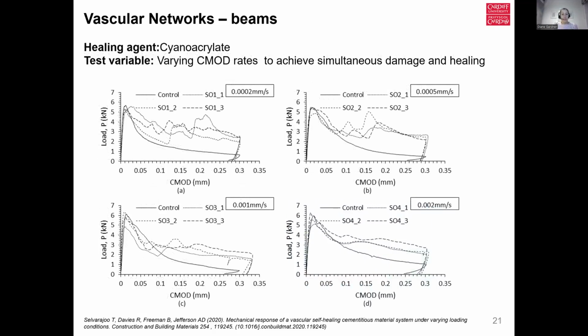Here we have slightly different tests to the ones I've just seen on the previous slide, in that we have varying CMOD rates to achieve simultaneous damage and healing in our specimens. So the results differ from those in that the post-heal peak loads are significantly lower than those of the fixed static crack tests. The post-healed responses exhibit lower average rates of softening, and the post-healed responses exhibit multiple peaks for nearly all specimens tested. It is believed that these self-healing responses indicate that multiple healing damage events occurred and that damage and healing progressed simultaneously.